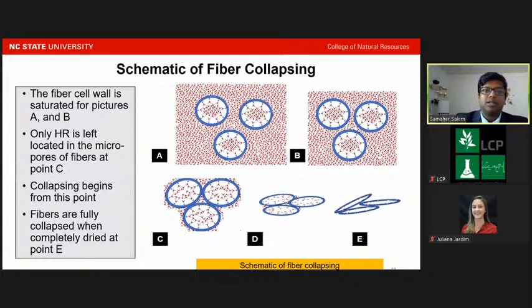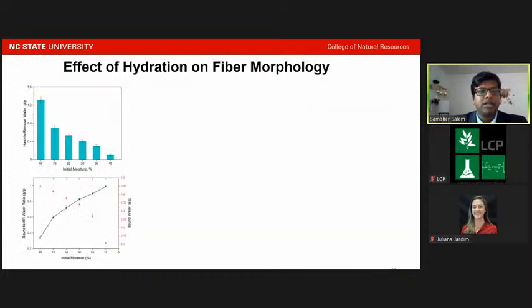And this is the schematic representation of the fiber collapsing. The fiber cell wall is saturated in figures A and B, and only hard to remove water is left in the lumen, as shown in C. As we try to dry it more, the collapsing begins and the fiber fully collapses when almost all the water is removed at point E.